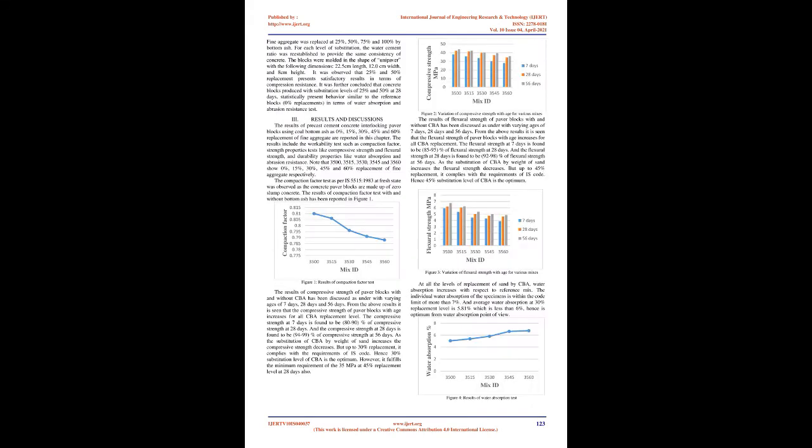It was noted that the strength of bottom ash concrete with 10% replacement is higher compared to concrete without bottom ash for all W/C ratios. Rauret et al. studied the strength performance of concrete using bottom ash as fine aggregate at 5%, 10%, 15%, 25%, and 30% replacement levels, adding microsilica at 4%, 6%, 8%, 10%, 12%, and 15%. Ordinary Portland cement, OPC, 53 grade with consistency of 35% was used.